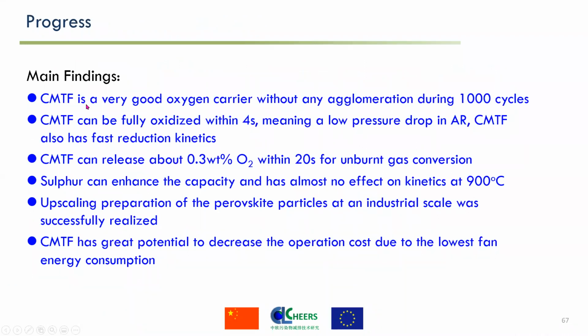In summary, CMTF is a very good oxygen carrier without any agglomeration during 1,000 redox cycles. CMTF can be fully oxidized within just 4 seconds, meaning a very low pressure drop in the air reactor. CMTF also has faster reduction kinetics. CMTF can release about 0.3% oxygen in the air reactor, with just 20 seconds for unburned gas conversion. Sulfur can enhance the oxygen transport capacity and has almost no effect on the kinetics at 900 degrees.